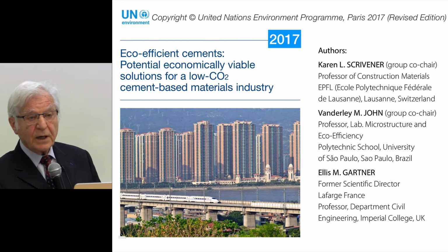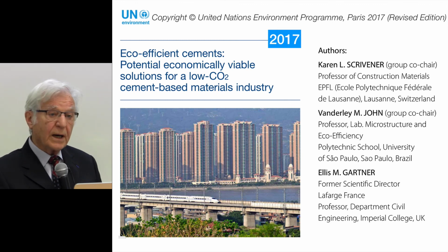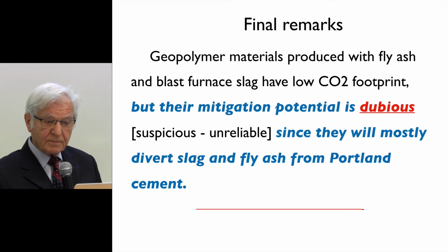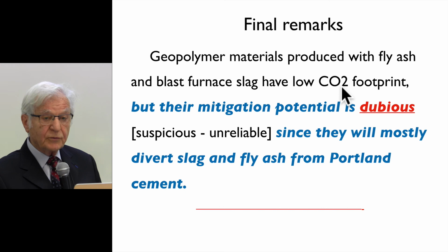And they claim, well, we can reach 10%, we can reach 20%, and so we can reach maybe 30%. And they also talk about geopolymer cement. Final remarks. Geopolymer materials produced with fly ash and blast furnace slag have low CO2 footprint, but their mitigation potential is dubious, since they will mostly divert slag and fly ash from Portland cement.